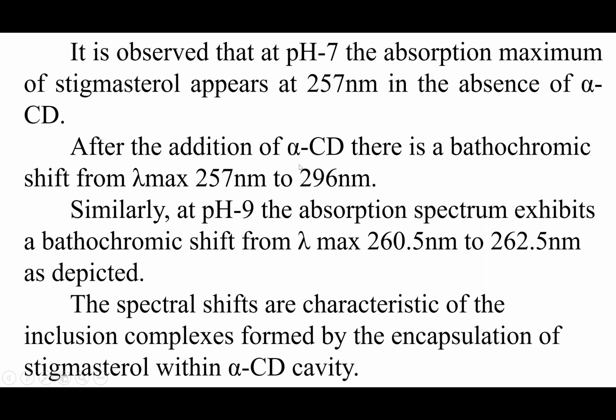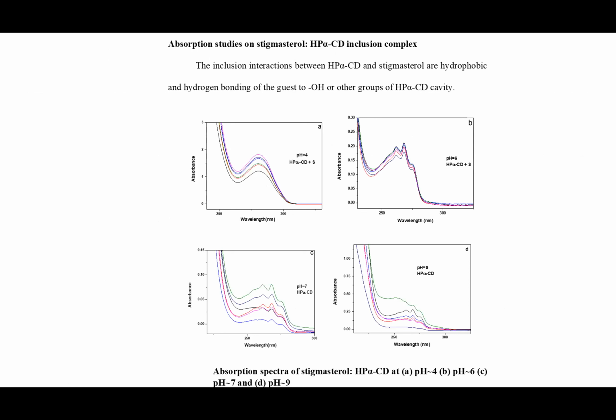So all these spectral changes indicate there is an inclusion between stigmasterol as well as alpha CD. So this is for hydroxypropyl alpha CD and stigmasterol complexes at varying pH. This is for pH 4, and this graph is for pH 6, and this is for pH 7, and this is for pH 9. Here, the absorbance also varies, but for pH 4, there is no change in wavelength, but the absorbance varies. Here, there are different peaks obtained when we vary the concentration of HP alpha CD.